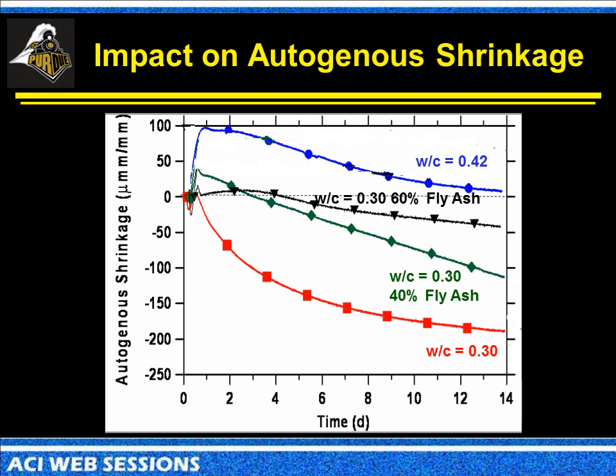And remember, this is autogenous shrinkage that's occurring if you've got perfect curing conditions, you're not losing moisture to the environment, you're not having a temperature change. We're going to be building up stresses inside the system. If you had a higher water to cement ratio, you might see a slight expansion, but then you're going to start to see some autogenous effects taking place. 40% fly ash, you're seeing what happens here. 60% fly ash, a little bit lower autogenous shrinkage early on.